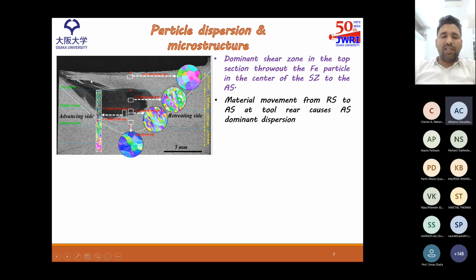And this happens only in the top layer, because in the top layer, a shear zone is formed around the pin. This shear zone is very dominant in the top section, which throws out the particles from the stir zone to the advancing side. Now, why only the advancing side, not the retreating side? Because the material movement is from the retreating side to the AS at the tool rear, which causes the dominant dispersion on the advancing side as compared to the retreating side.